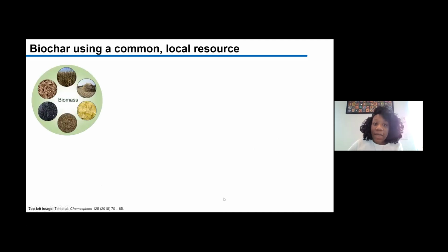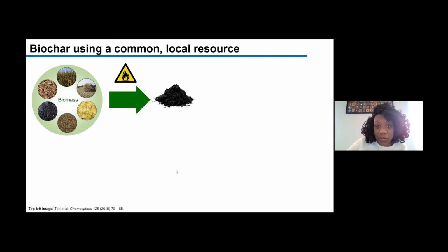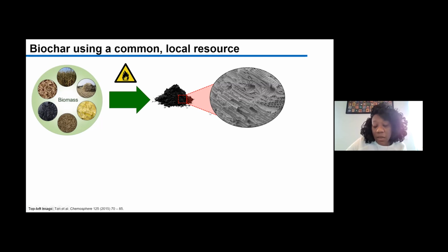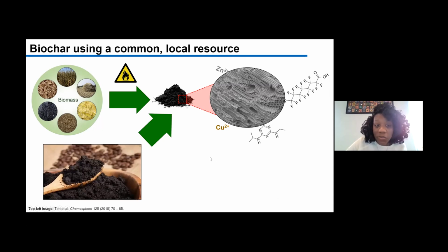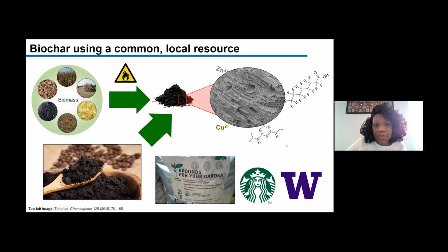Okay, one more highlight of the materials that we're developing in the lab to help remove contaminants in these systems is a material called biochar, which you might have heard about before. The bio in biochar comes from biomass. So you typically use some agricultural or food waste product to burn at high temperatures, and it produces a charcoal material essentially. And if you take an electron microscope image of this char, you can see very nice open pore-like structures inside, which are very effective for trapping contaminants in stormwater. For our particular biochar, we're using used coffee grounds, which I think is pretty fitting. Seattle's the coffee capital of the world. So we have a lot of food source available to us to use. In fact, we're getting ours from campus, and I believe the campus is getting their coffee grounds from Starbucks. So again, lots of source material available to us.